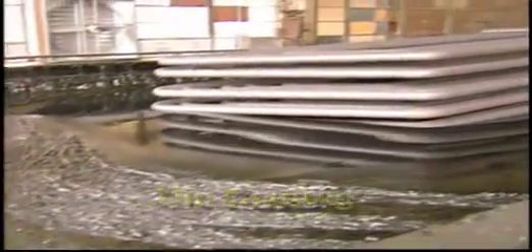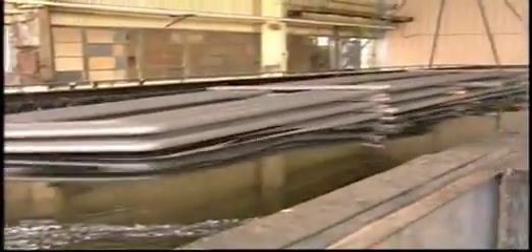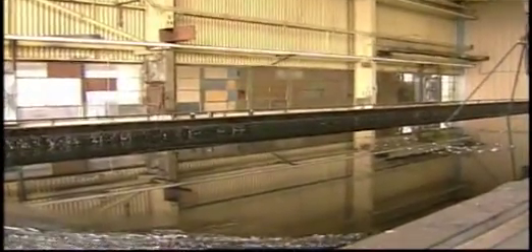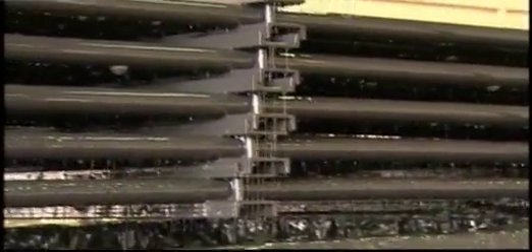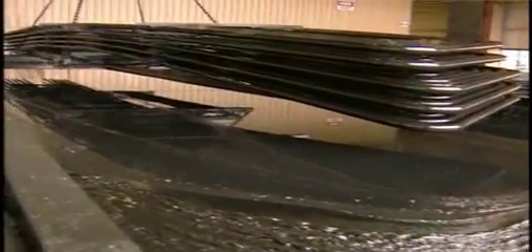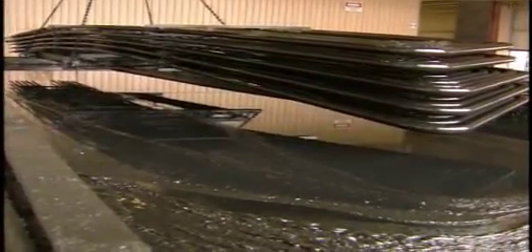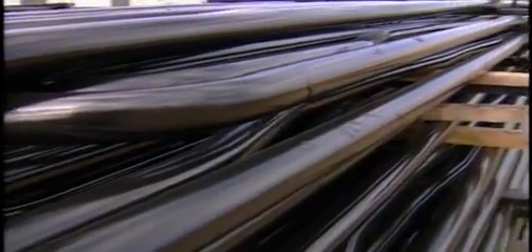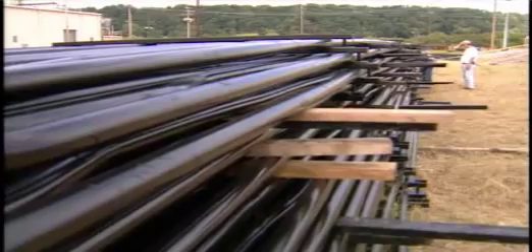Dip coating involves the immersion of individual parts into a tank containing the coating. The parts, usually on hangers or trays, may be dipped individually, in batches, or by a continuous conveyor line. After the coated parts emerge, they may be held over the tank to allow the excess coating to drip back into the tank, or they may move to an area where the excess coating is collected and returned to the tank. The coating in the tank is kept at a constant solids concentration by the addition of fresh coating and solvent to make up for usage and evaporation. Transfer efficiency for dip coating is approximately 85%.